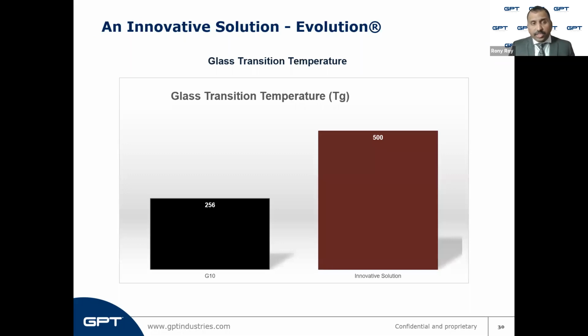The other requirement that was analyzed during our changing conditions slides was the temperature requirement of the materials. GRE G10 and G11, as we saw, have a temperature rating of 150 degrees Celsius. G10 is 150 degrees Celsius maximum, and G11 is 200 degrees Celsius maximum. Evolution is rated to 500 degrees Fahrenheit or 260 degrees Celsius, and has shown very little degradation even at temperatures higher than that. It looks almost like the test was run at an ambient temperature when you compare these two graphs against a G10 material, which becomes a molten mess by the time it reaches the temperature limits of Evolution.